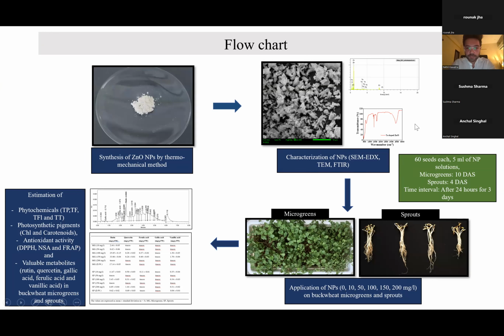After this, the nanoparticles were sprayed on microgreens and sprouts at different concentrations. After this, the extract of the microgreens and sprouts were prepared for the analysis. And in the analysis, we performed the phytochemical analysis. We analyzed various photosynthetic pigments and also the effect of various antioxidants that are present in microgreens and sprouts. After this, by using ultra-performance liquid chromatography, we also analyzed the effect of nanoparticles on the content of rutin, quercetin, gallic acid, ferulic acid, and vanillic acid in both buckwheat microgreens and sprouts.